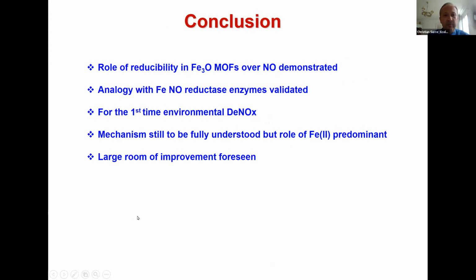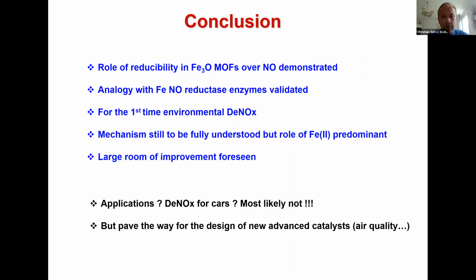So as a conclusion for this part, we have shown that reducible iron MOF have strong interaction with NO. And for the first time we could demonstrate the possibility to do environmental DeNOx reaction through an analogy with the NO reductase enzyme. The mechanism is still to be fully understood, but there's a role of iron(II) that is important. And from the materials point of view, we see a large room for improvement. Of course, it probably cannot be applied for DeNOx in cars because of the temperature, but we could imagine many other catalytic processes, for instance for air quality, to combine capture of VOCs and NO degradation to destroy VOCs at ambient condition.